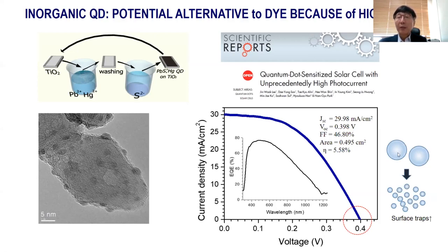However, when you decrease the particle size, you at the same time increase the surface traps, which can act as recombination centers. Therefore, you cannot expect a high open circuit voltage. Even though the band gap is 1.1 eV, you have around 0.4 or 0.5 volt. Therefore, the inorganic quantum dot was not successful in replacing the organic sensitizer.